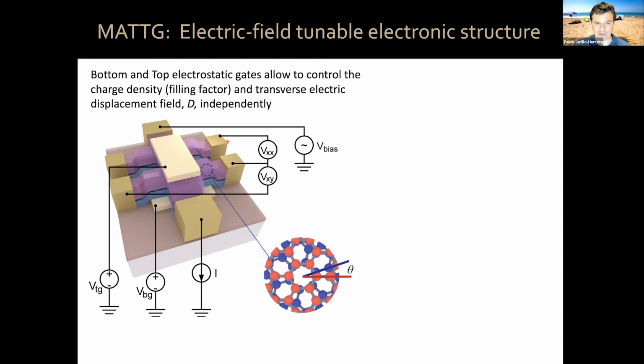It's contacted by source and drain electrodes in a Hall bar geometry. And then we have a bottom and a top gate. With these bottom and top gates, we can independently control the charge density or filling factor by applying, for example, the same polarity to those gates. And independently, we can control the transverse electric displacement field by applying opposite voltage to those two